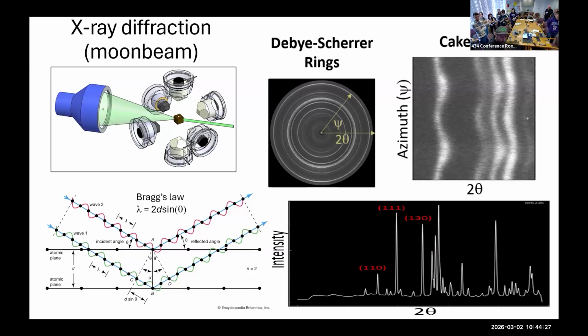So you'll get a diffraction peak at a particular position. And then, of course, the crystals are going to have more than just one crystallographic plane. They've got a bunch. So you're going to get a bunch of circles. And then if you just add up around the circle where they're all the same radius, you can get the single 1D diffraction pattern, like you're perhaps more familiar with. When you put stress on it, you start to get these squiggles. We'll talk about that in a second.